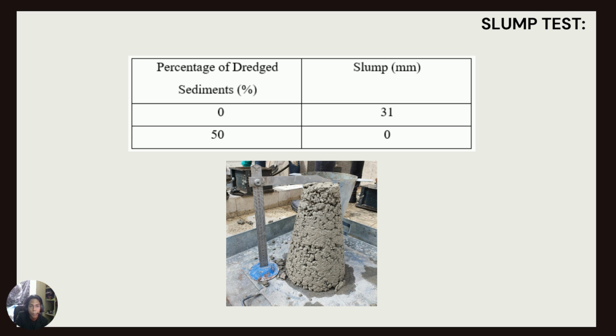Next, for the slump test, the conventional concrete slump is 31 mm. Meanwhile, the dredged sediment concrete is 0 mm. The slump shows that it is in the category of zero slump concrete. Basically, the slump portrays that the concrete maintained the actual shape of the mold, showing no measurable slump after removal of the slump cone. However, zero slump concrete is used for the production of concrete mass products. As for the conventional concrete, the slump obtained was 31 mm and was categorized as a true slump.